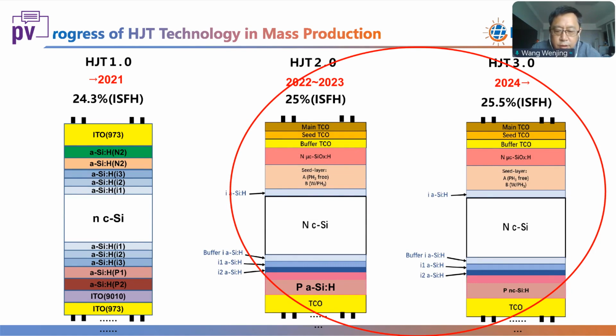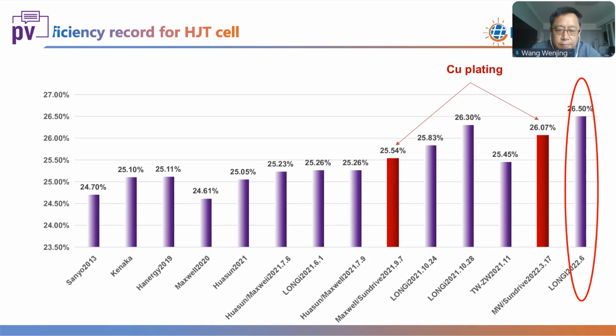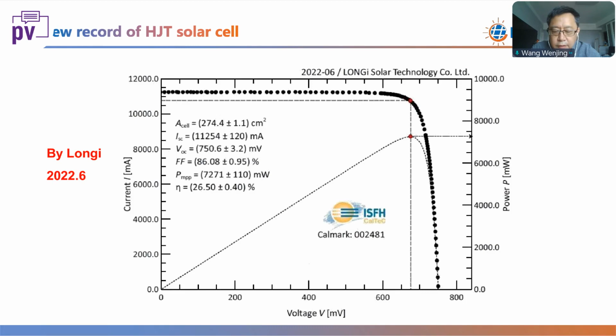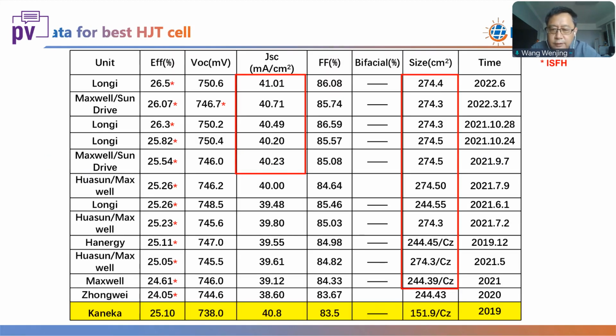As for HJT 2.0 and HJT 3.0, there are already many companies making huge progress. Last year, there were many breakthroughs of the world record. The newest result is just this year, June this year. The efficiency already arrived at 26.5%, by LONGi. Here is the IV curve of LONGi. From the data of this new technology, we can see the current increases very fast. Very recently, LONGi's world record is 26.5%. The JSC already arrived at 41 milliamp per centimeter square.